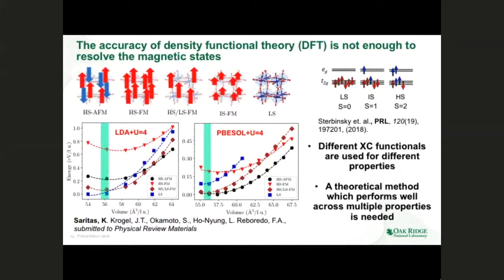Depending on how these are oriented, this is not a complete span of all the magnetic structures that can exist in lanthanum cobaltite, but these were the ones studied most often in the literature. We need a method that can perform well. Maybe we can use a DFT method, which does well on geometry optimization, but use diffusion Monte Carlo to understand which magnetic structure is going to be the ground state here.